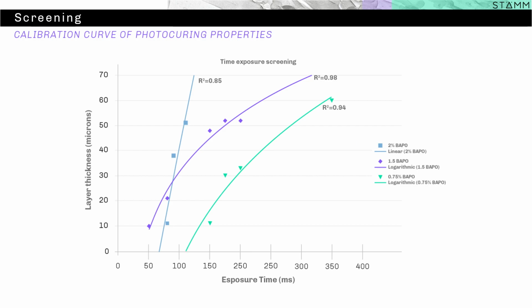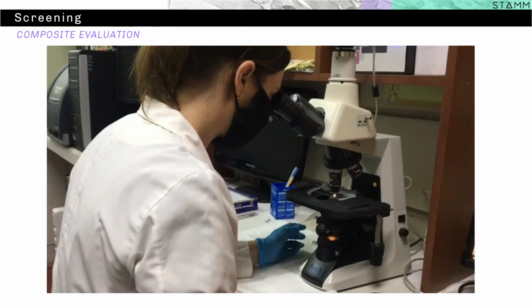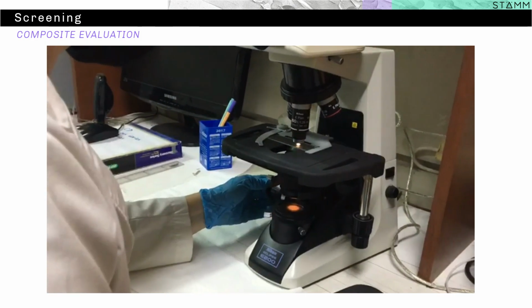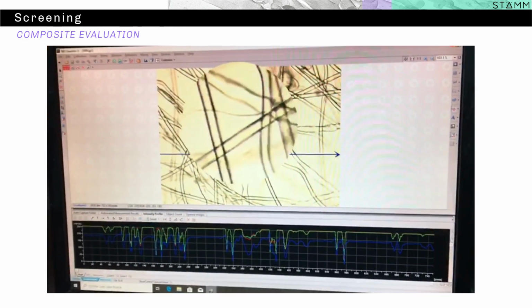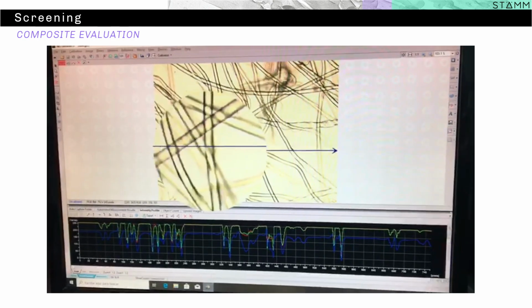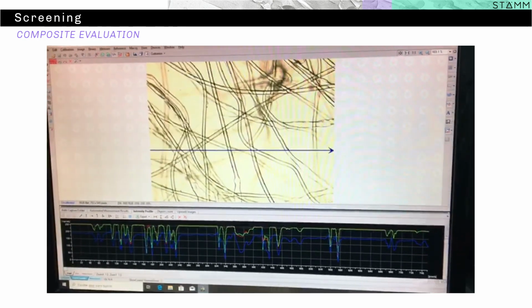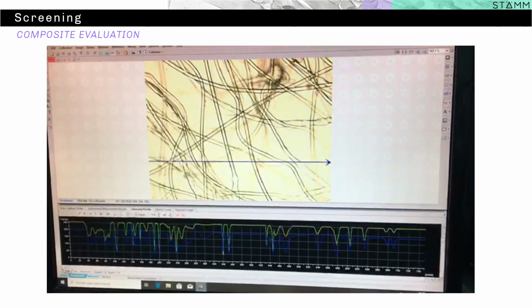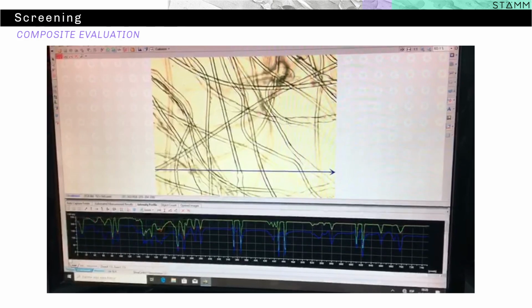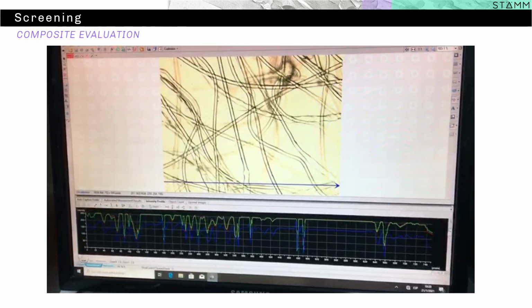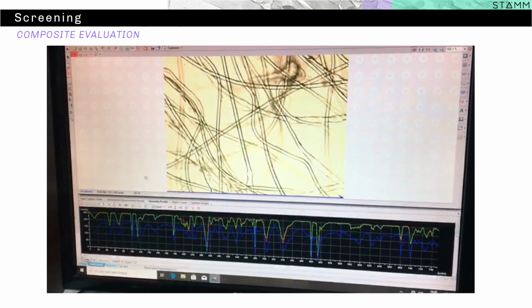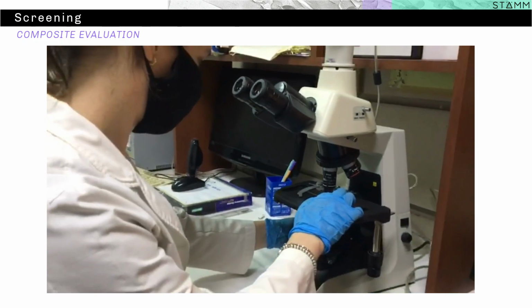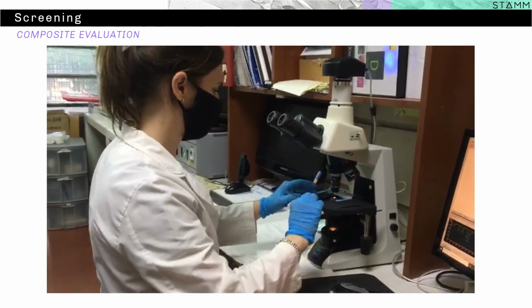With these curves, now we are able to see the performance of a photocurable biomaterial to define the suitability of this resin. And once we have detected these pre-candidates that are compatible with the photocuring process, we proceeded to evaluate their properties as printable composites. To guarantee the resistance to mechanical stress, porosity, structure, and biocompatibility of the biomaterial, different parameters were studied in order to homogenize the light curing process, as well as to describe the arrangement of the microstructures and to manipulate the delivery of the non-reactive compounds after the printing process.